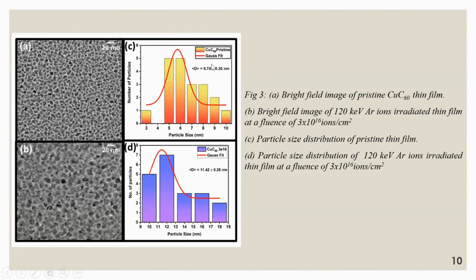These are the TEM images. This is a TEM image of the pristine CuC60 nanocomposite thin film, and this is the TEM image of the CuC60 film irradiated at 3E16. So we have seen the increase in the nanoparticle size. The nanoparticle size increased from 5 nanometers to 11 nanometers.